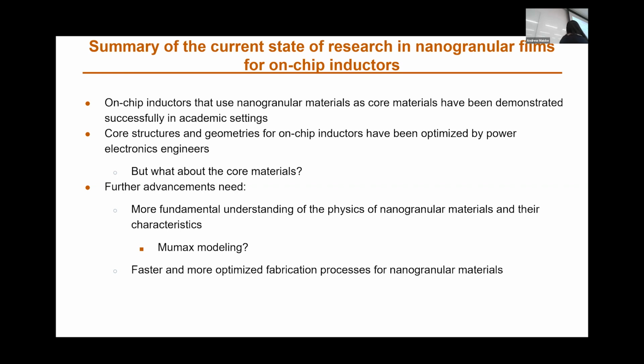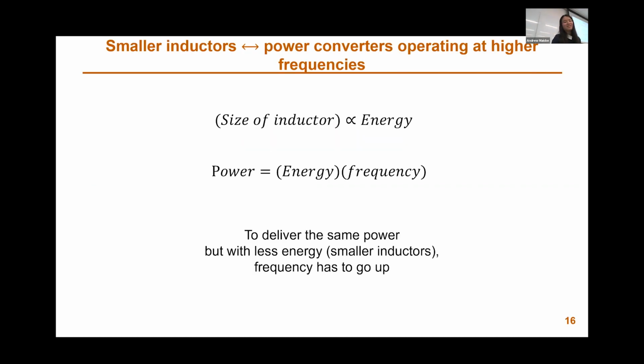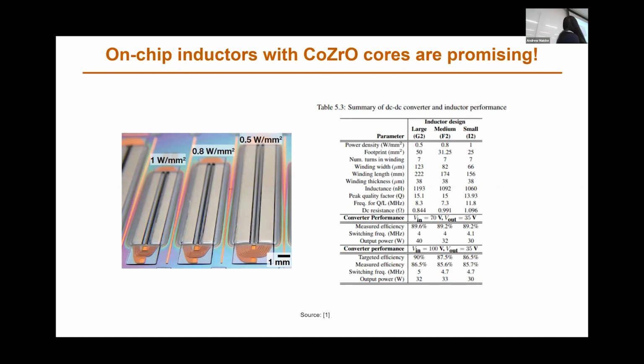And it's a brief summary now of the state of research on on-chip inductors right now. In general, people have made on-chip inductors with these nanogranular materials, specifically cobalt zirconium oxide, and with relative success, actually. This group has made a converter with 90% efficiency using these inductors, which is higher than the efficiencies of on-chip integrated power converters you'll find on the market, which are typically around 60 to 70%, so much higher.